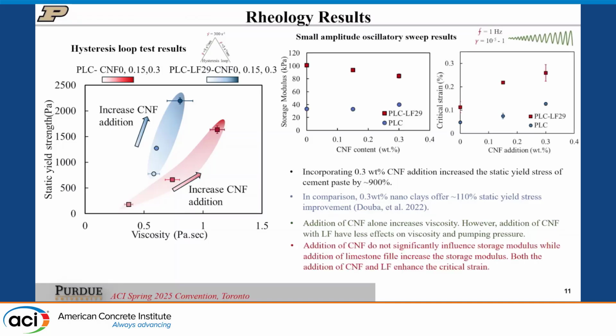For those rheologically interested, let's look at storage modulus and critical strain. For the PLC mixes, the blue dots, we don't see significant increase in storage modulus alone, which agrees with what we saw in the calorimetry. But with the PLC limestone system, we see somewhat of a decrease in storage modulus with adding more CNF - those are the red squares up top. So by adding more CNF, we are decreasing the storage modulus.